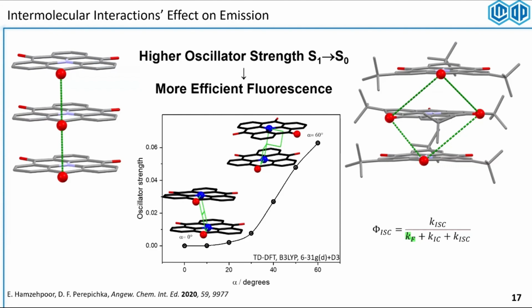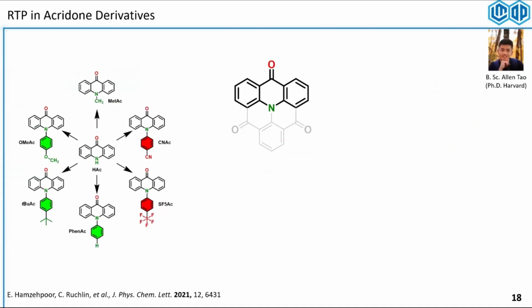It just stays there until some other pathways, like the intersystem crossing or non-radiative decays, would start to consume it. And that's probably how we got phosphorescence in this system. So I got greedy. I said, okay, now we found the design principle, changing the substituent, looking at the emission. Let's try this with other derivatives as well.